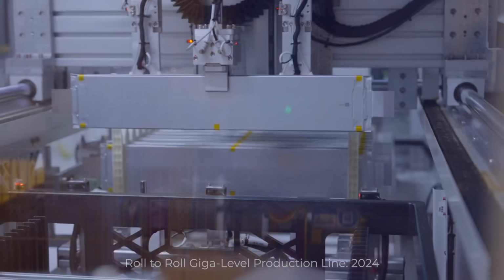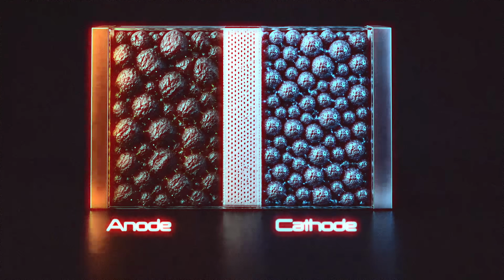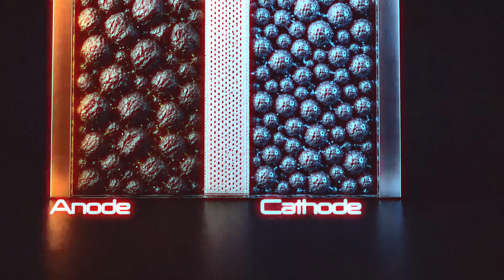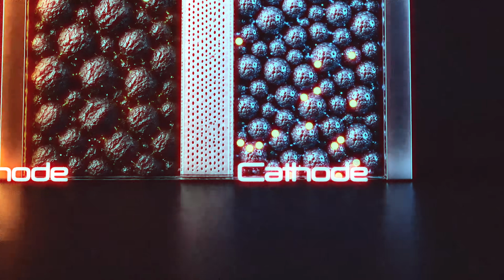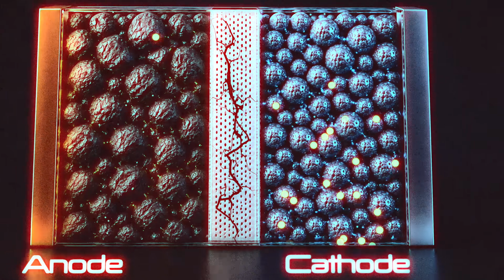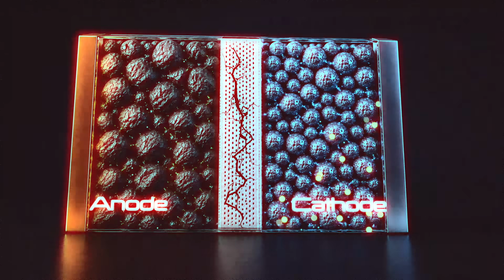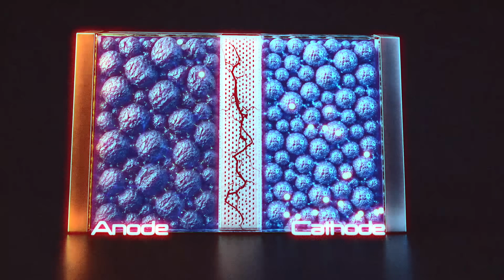Let's start with the safety problem because it's probably the most important for consumer trust. When a lithium-ion battery overheats, 3 things happen at once. First, the charged cathode, usually a nickel cobalt manganese oxide or NCM, starts releasing oxygen at around 150 degrees Celsius. Second, the oxygen reacts with the charged anode, which is essentially a reservoir of lithium energy that desperately wants to combust. Third, the flammable liquid electrolyte between them ignites and fuels the whole thing.